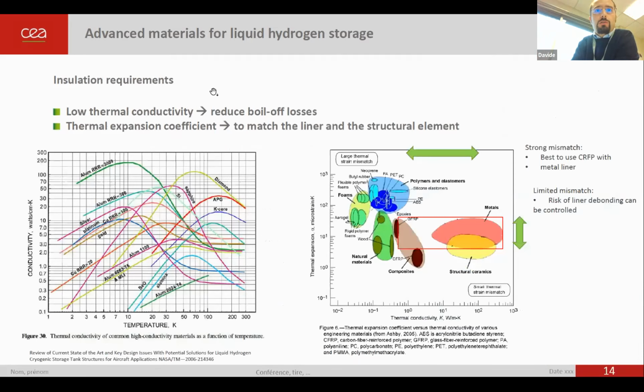So in terms of requirements, we have to deal with low thermal conductivity. I will go very briefly through this slide. The idea is to look for low thermal conductivity material to reduce the boil-off losses, with matching thermal expansion coefficient. If you want to go for a tank with a liner, we normally use metals, and of course the compatibility in terms of expansion coefficient between the metals and the epoxies or the carbon fiber materials has to be managed in order to avoid delamination, infiltration of air, and solidification within the matrix.